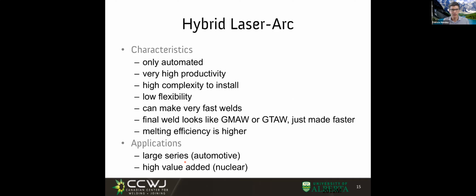Has very low flexibility, but once it's running, it can make these very, very fast welds. The weld in the end looks just like a normal MIG weld, just you made it so much faster than a MIG weld. The melting efficiency is also higher because you move so fast. You don't give a chance for the heat to dissipate into the rest of the base material. So distortions are lower. Where do you use these? For large series in automotive or very high value added processes like nuclear.